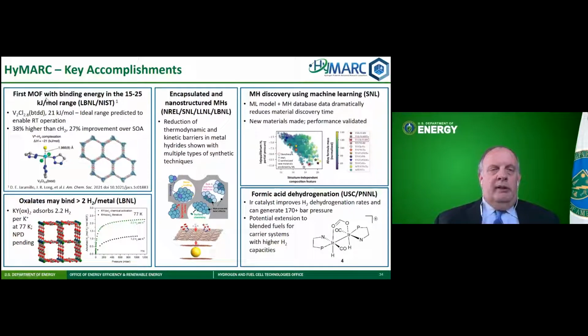For hydrogen adsorbents, one of the issues with hydrogen adsorbents is that the binding energy of hydrogen is too low. So after operating at cryogenic temperatures, it's been projected we need a 15 to 25 kilojoule per mole binding energy to be at room temperature. They just reported in the Journal of the American Chemical Society, JACS, a new vanadium MOF material, which actually has an isosteric heat of adsorption of 21 kilojoules per mole, right in that ideal range. The capacity is still low, but it's still 38% better than compressed gas, and it's a 27% improvement over any of the other state-of-the-art adsorbents at room temperature. So that's an exciting new development.